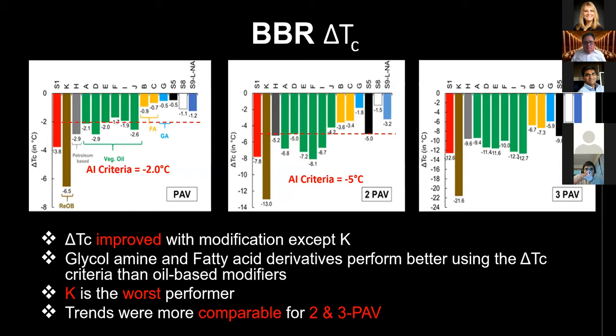National research projects have indicated that delta TC is a parameter that has promise in the prediction of modified binders' long-term performance. Delta TC serves to quantify the non-load cracking behavior of binder that is affected by the asphalt binder's diminished relaxation properties. The lower the delta TC, the more susceptible the binder is to low temperature cracking. The graphs on the slide from left to right increase PAV aging.